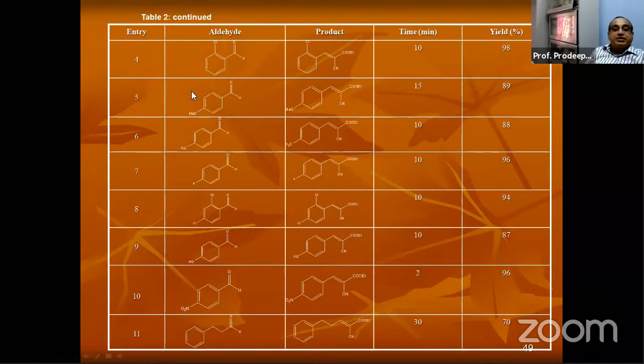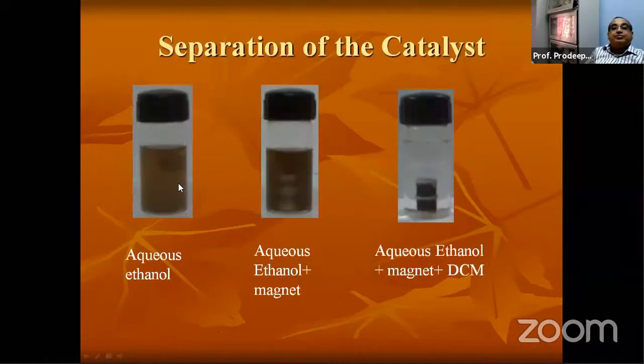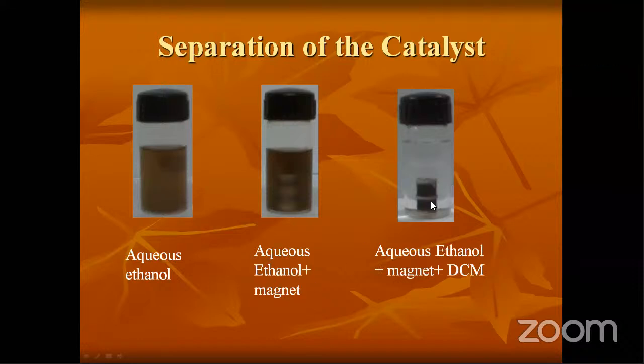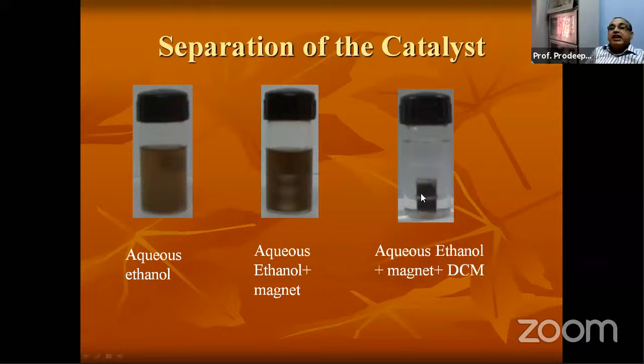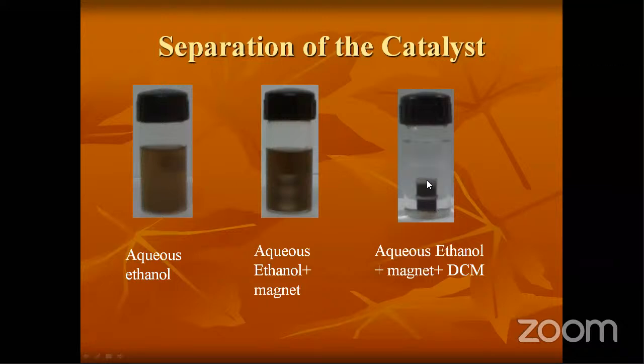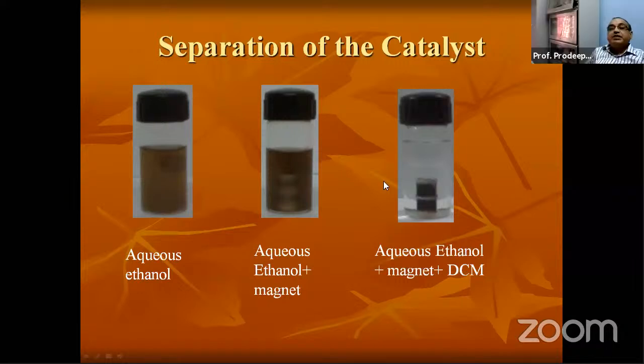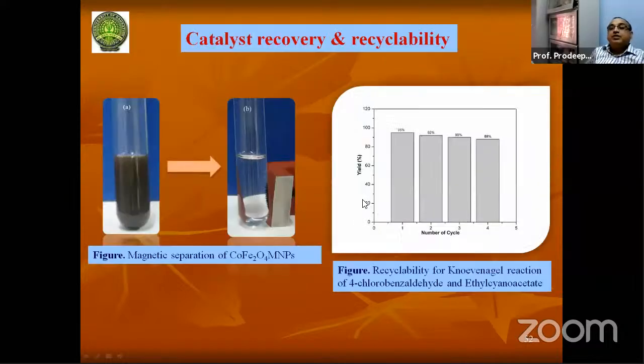Then this is the separation you see. This is aqueous ethanol, this is aqueous ethanol plus magnet, and here you put some DCM, immediately it gets attracted to the magnet. It's very clear, so that means you can very easily separate it. And this we have already shown. After separation, 95, 92, 90, 88% up to 4 cycles, it is quite impressive.